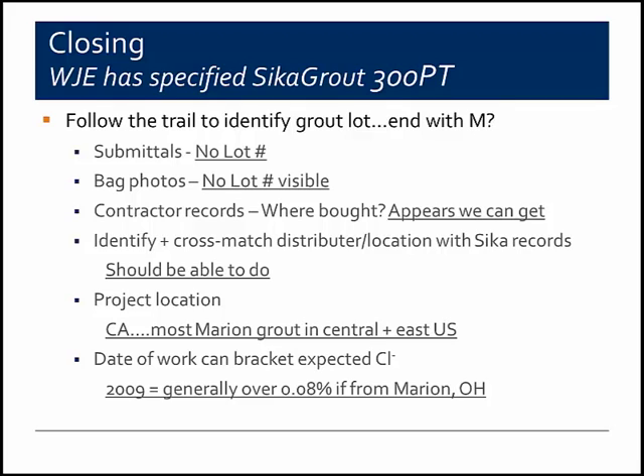And the project location can also be helpful to identify if it's likely grout from Marion, Ohio. This particular project is in California, and most of the Marion, Ohio grout ended up in the Midwest or on the East Coast. Very little went to California and the western states. Also, the date of work can bracket the expected chloride content as shown in the graph. If we're talking about a project from 2003 or 2004, in general, the chloride contents that have been determined from both field sampling and retains are lower, not necessarily above the specified limit.